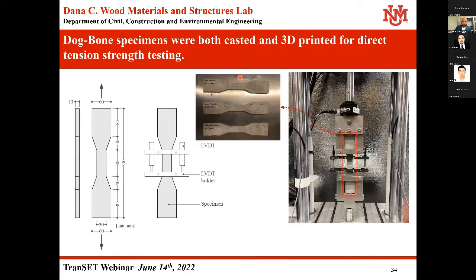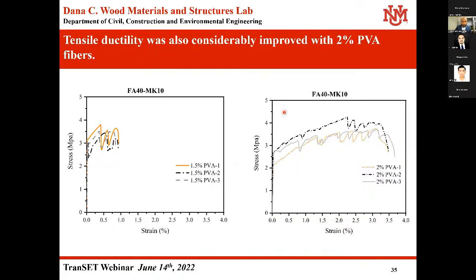For the tensile ductility, we used a 3D printed dog bone specimen, and the results you can see at 1.5% inclusion of fiber and 2% fiber. With the addition of 2% fiber in the mix, the tensile ductility was considerably improved as compared with the 1.5% fiber in the mixes.